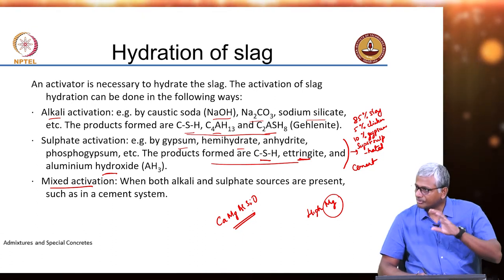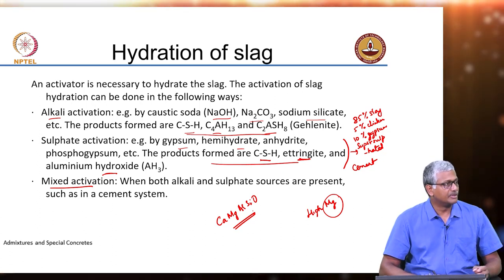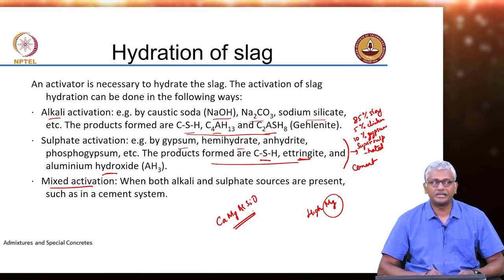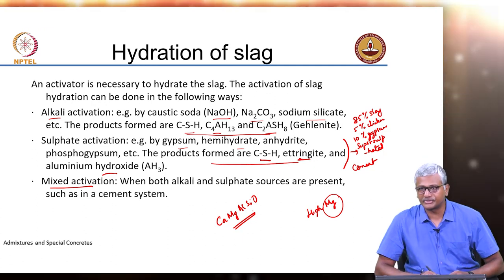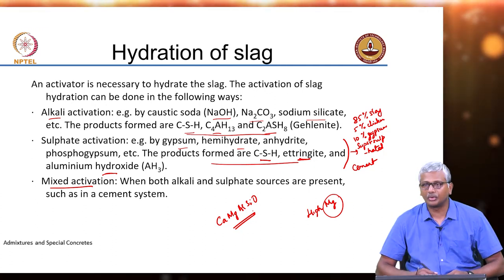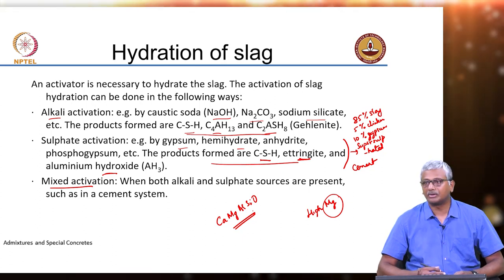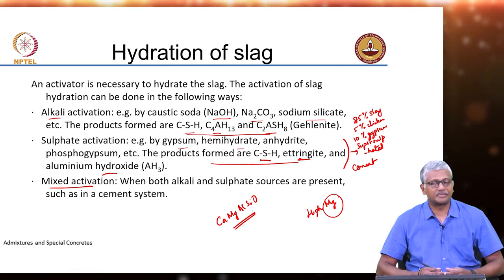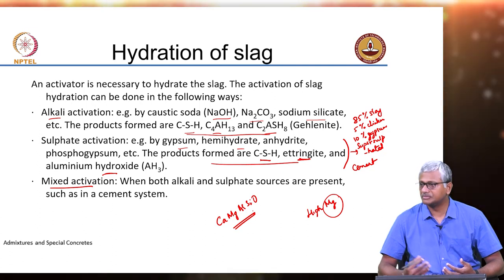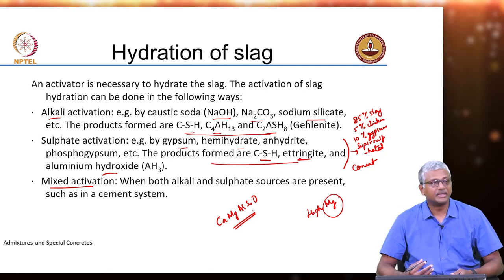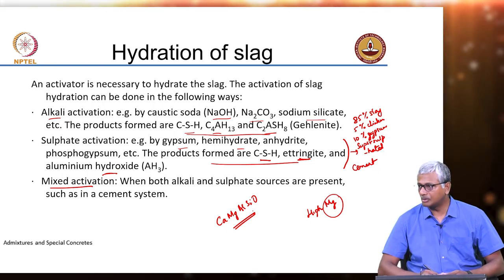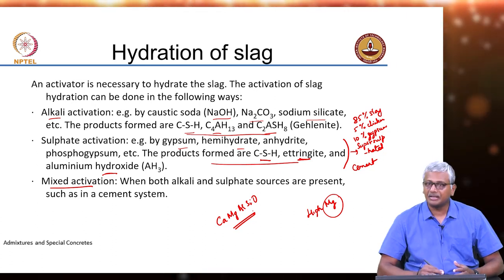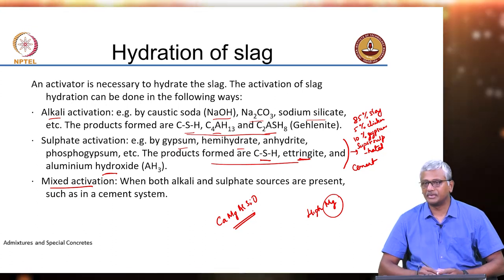So the greater the amount of free amorphous silica that is present, the faster will be the reactivity. But for these magnesium-containing phases, getting them to react in any short period of time is very difficult — it is only a long term process, and by then the water available for curing or hydration will have already been mostly depleted. So most of the reaction will happen because of the amorphous phases present. All slag is amorphous, but the amorphous phases containing magnesium are not that easy to come into solution and undergo reaction.